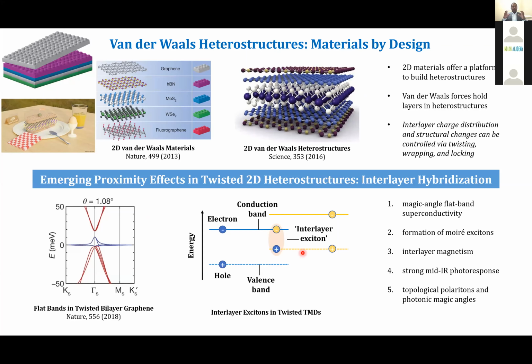And then also if you build with MoS2, like transition metal dichalcogenides, if you put two transition metal dichalcogenides on top of each other, then what you will observe is called an interlayer exciton. So we have excitons, it's a bound electron-hole pair. And most of the time, we have studied that these excitons can be in individual materials. However, if you stack these materials, you will be able to see interlayer excitons. That means electrons from one material and holes from another material can form the exciton. So that's called an interlayer exciton. Not only that, interlayer magnetism, strong mid-IR photoresponse, topological polaritons, and photonic magic angle. So these are all new physical phenomena that have emerged in the heterostructures.